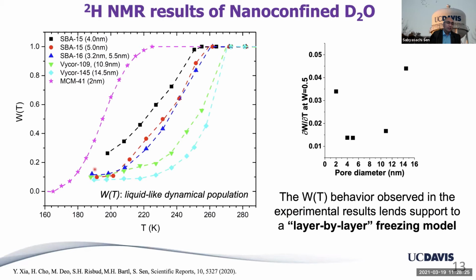So this is not difficult to understand if one realizes that for the smallest size pore, it's probably very difficult to have multiple layers with different types of water structure inside the pore. It's probably all very homogeneous because it's just 2 nanometer size, and all the water is behaving identically and they freeze within a very narrow range.